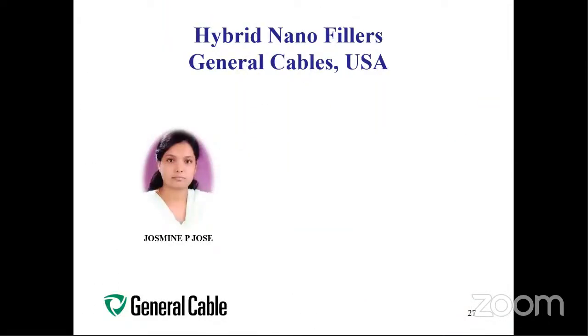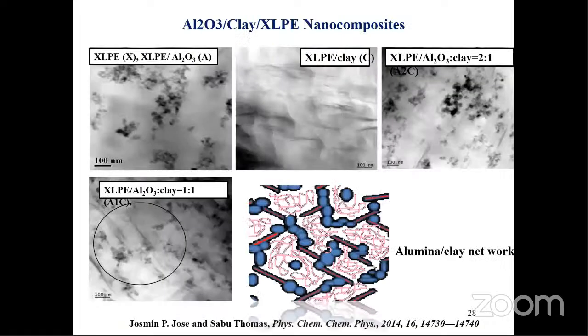Let me show you another example. We had a very strong cooperation with General Cable, United States. A PhD student of mine, Josmine P. Jose, made use of different types of nanofillers. You see, we mixed the clay. This is XLPE matrix with aluminum oxide. You see a lot of clusters. We could not disperse aluminum oxide in the XLPE matrix. We put in clay. Clay got a reasonable dispersion, 5% of clay.